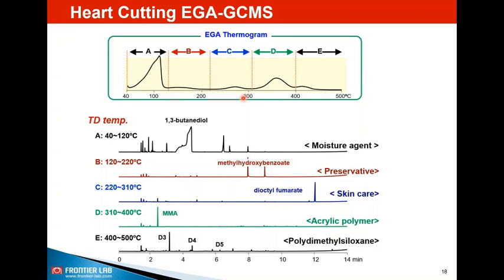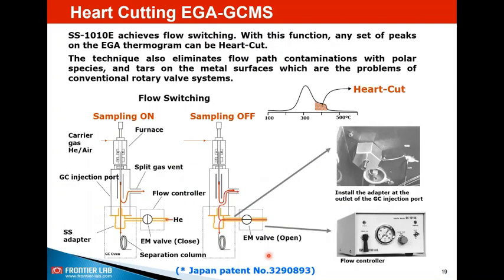Now, heart cutting, at least in terms of the concept, you are basically cutting the first peak from the micro furnace temperature zone, then you transfer this to the GC column for separation. Similarly, you repeat this for each zone, whereby you are able to get 5 different chromatograms from a single sample. How is it working? We have this accessory called the Selective Sampler, because you have to have some kind of control over which fraction you want to transfer to the GC and which portion you want to hold. This is what the Selective Sampler can do for you.